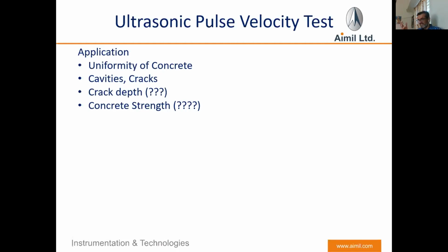The point I'm trying to say is, in case of M10 grade concrete, where M10 means 100 kg per cm square concrete, if it is very well compacted and well executed, your velocity value will be very high because it gives the uniformity of the concrete, but since it is M10 grade, the compressive strength will be less. In the same way, if your M40 or M45 grade concrete is not well compacted or well executed, it will give you low pulse velocity, but since it is M45 grade concrete, overall it should be high compressive strength concrete. So as per my understanding and personal opinion, as per my exposure to this range, both things are separate and cannot be correlated. But maybe after some years there may be some correlation.